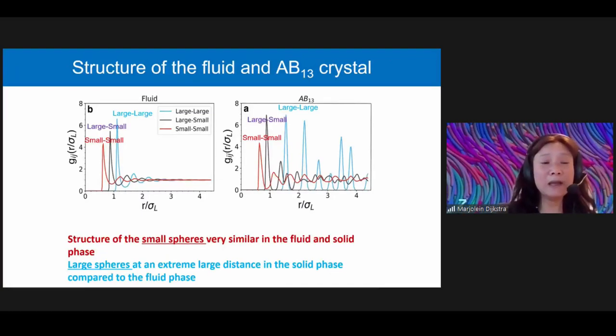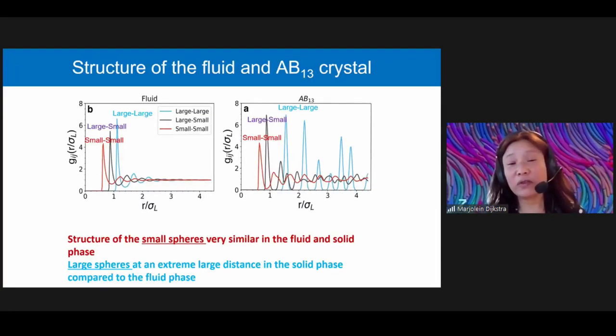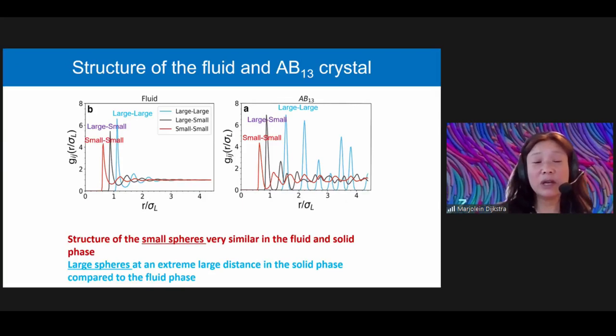If you look at the structure of the fluid in the AB13 crystal phase, then one can notice that the structure of the small spheres is very similar in the fluid phase as in the AB13 phase. So this really makes it very difficult to distinguish the fluid phase from the AB13 crystal phase and to study nucleation in the system. Moreover, the large spheres are really pushed apart from each other in the AB13 crystal phase, and that makes it difficult to identify the neighbors of the large spheres by just using a simple distance criterion.